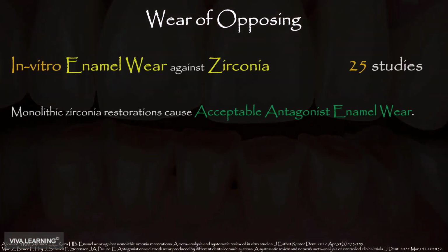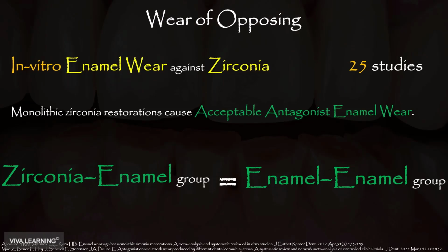The best way to answer is by looking at a systematic review that evaluated 25 studies on the wear of enamel versus zirconia, and they concluded that the wear of the zirconia-to-enamel group has been similar to the enamel group in all the studies, with the condition that zirconia needs to be really polished. Glazed zirconia wears enamel more. A rough zirconia wears it more. It's really crucial to have a very polished zirconia in order to have it as wear compatible as possible to enamel.